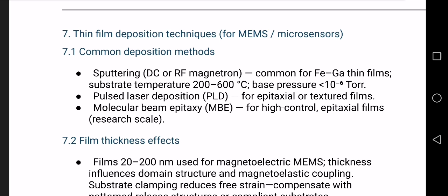Why is sputtering popular? Because it has good thickness control, uniform films compatible with MEMS fabrication. DC sputtering is used for conductive targets. RF sputtering for better composition control. Okay. Pulsed laser deposition, PLD, is mostly used in research.